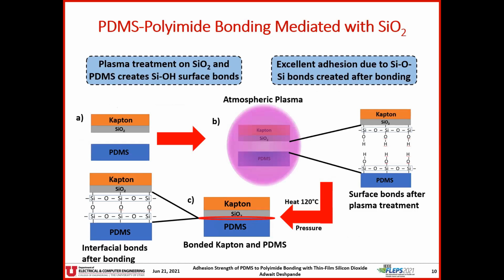In our approach, we use an interfacial SiO2 thin film for bonding PDMS and polyimide layers. SiO2 can be deposited using typical CMOS processes and is photopatternable, and hence selective bonding is possible. Additionally, bonding between plasma-treated PDMS and glass has been widely studied. There exists a strong bond between bonded PDMS and glass. This is due to the formation of SiOH bonds on the surface of PDMS and glass after plasma treatments and conversion of those bonds to SiO-Si bonds after bonding. This results in higher adhesion.